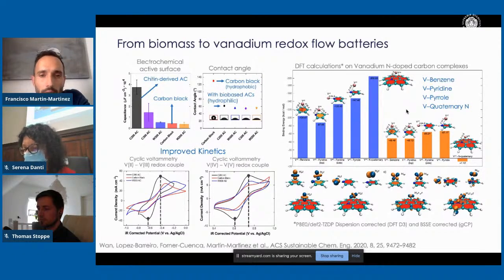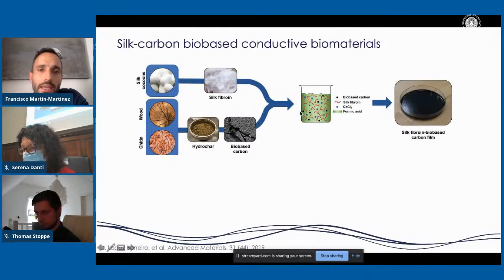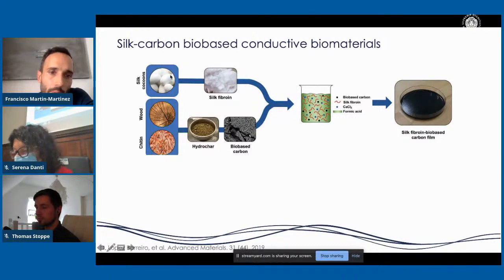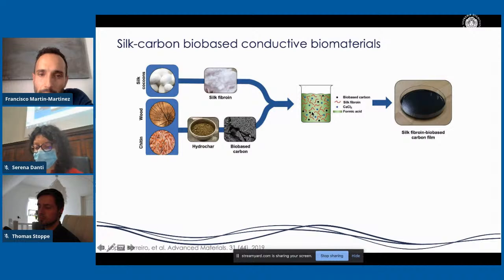The other project I wanted to comment on was how to combine these bio-based materials with biomaterials, basically to create conductive films that are biocompatible but also conductive. So what we did in this case is that we process silk coming from silk cocoons. We extract the silk fibroin, and we have a process in which we can create a solution of this silk fibroin. And in this silk fibroin, we put different types of carbon particles coming from biomass.